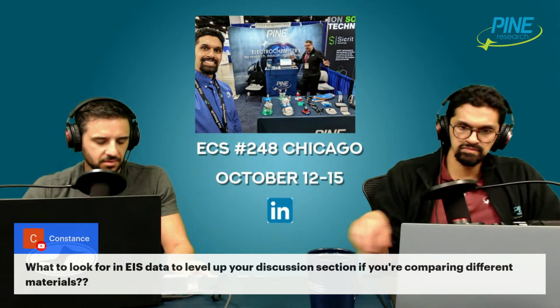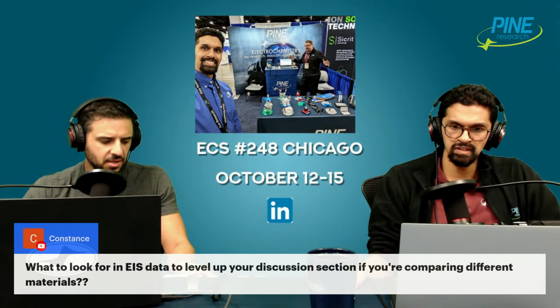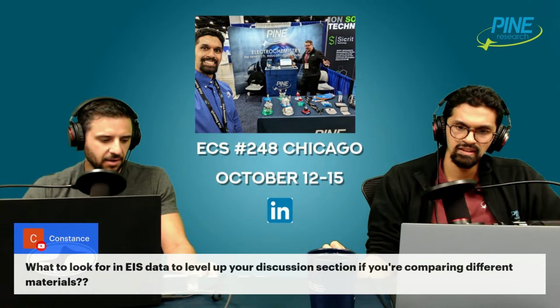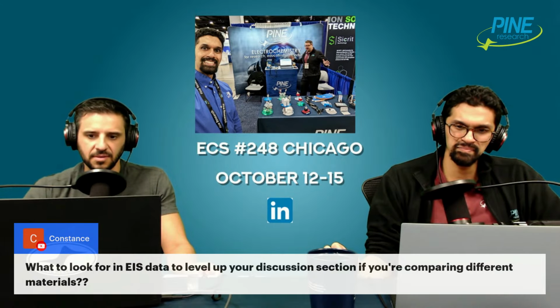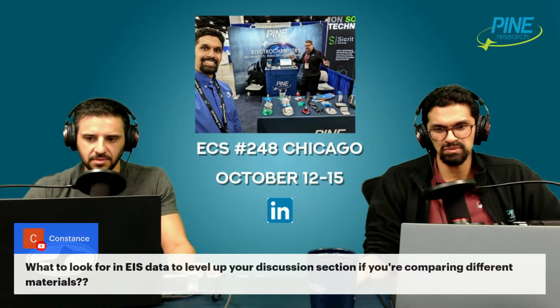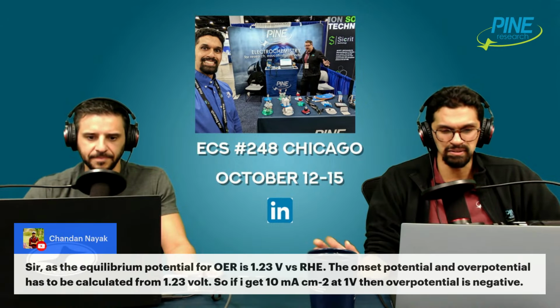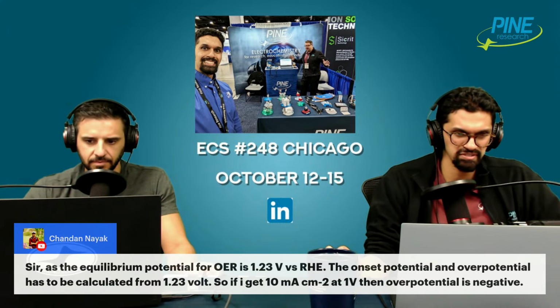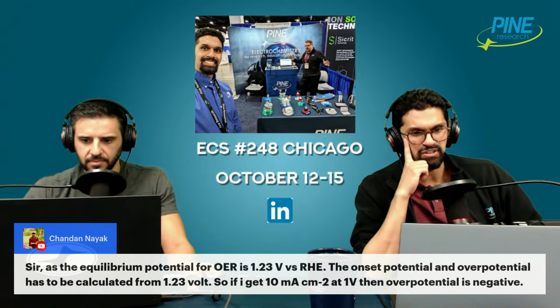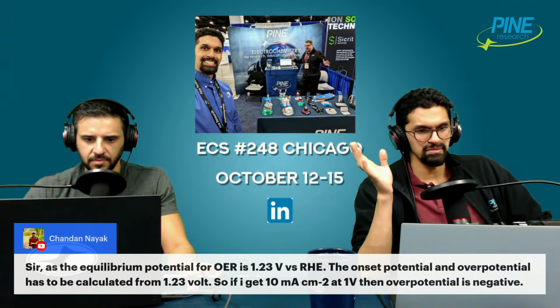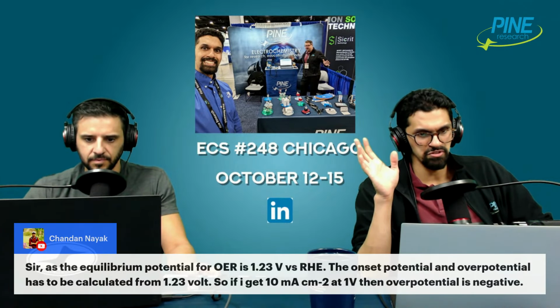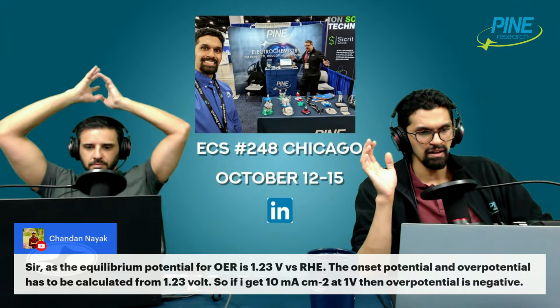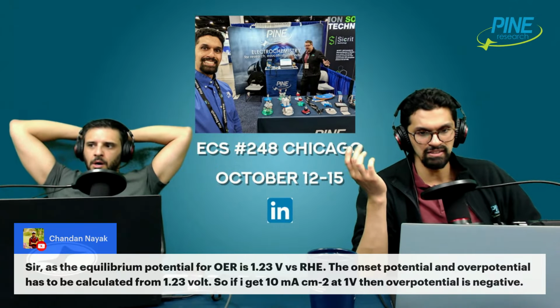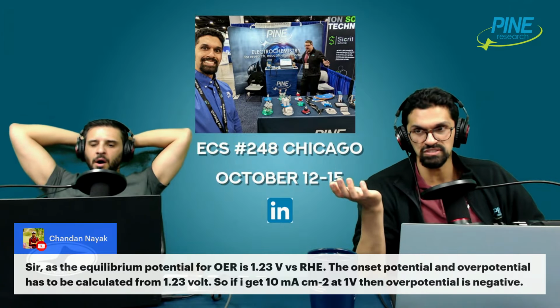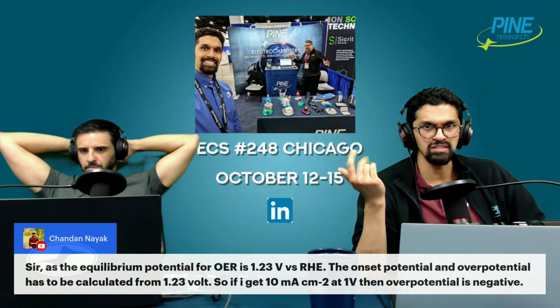There's a couple other questions. Chandan had just clarified about getting rid of those currents, so they're background currents. I don't know if there's much you can do about that. We can talk a little about Chandan's question, and this will probably be the last question. His argument is that if you're getting an onset potential that's 200 millivolts less than the standard equilibrium potential for OER, then you have a catalyst with a negative overpotential, an efficient catalyst, which is ideally something you want.